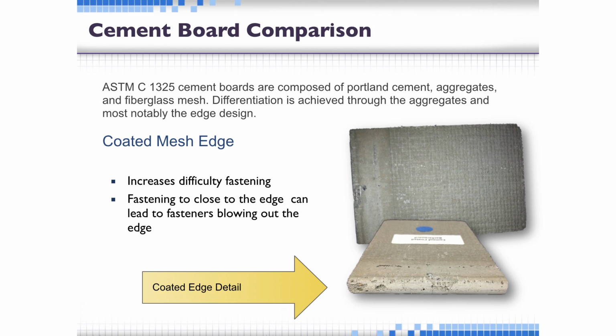So the picture is of Durock, and you can see there's some voids here. That's kind of, not Durock, it's Wonderboard. This is Wonderboard, so there's a few voids here. They do a little bit better job now of covering that, but the issue for you all is if you get your fastener too close to the edge, you're going to blow out that edge. And if you blow out the edge, you don't have any holding power, right? So it will vibrate, move, and then tile cracks on the interior, right? And it would be a problem for the exterior as well.